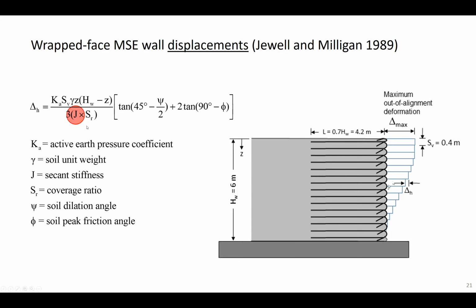And it's computed using this equation that you see here. And what you see is that this parameter J, which is the secant stiffness of the reinforcement, will play obviously an important role in this calculation. The rest of the terms are largely familiar. There's an active earth pressure coefficient, soil unit weight, coverage ratio, whether you've got 100% coverage of the soil layer going into the slide, soil dilation angle, and soil peak friction angle.